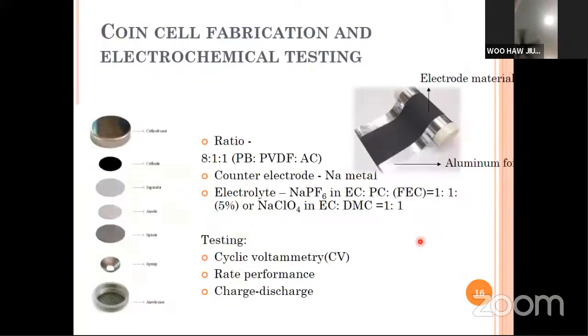So this is how we fabricate the coin cell to run the electrochemical test. First of all, the active material, the as-prepared Prussian blue, was mixed with PVDF as a binder and activated carbon in the ratio 80:10:10, and then we put the slurry on thin aluminum foil and dry it. Then we cut it into a circular shape. That is our cathode material.